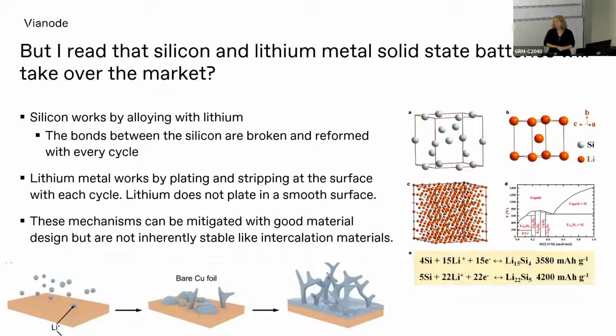So the other thing that people talk about is lithium metal, because of course, if you wanted to have a lithium ion battery and you didn't have a material to store the ions in on one side, you only had the metal that you're shuttling back and forth, then your energy density could be much higher. But what we see with lithium metal is that it stores energy through what's called a plating and stripping process. It's a metal, you're just plating it on the surface and you're stripping it off, kind of the way a lead acid battery works.